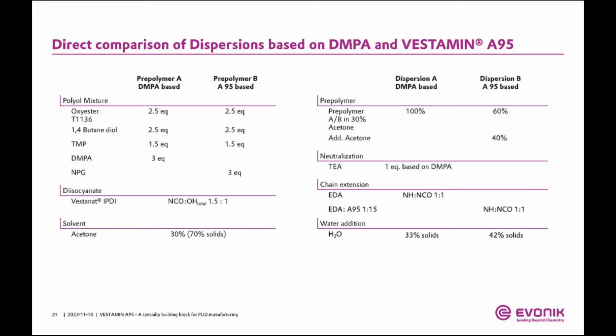In this case, with the A95, we do actually the chain extension and adding the emulsifier at the same point, right? When you use the DMPA-based method, you add the emulsifier right from the start in your prepolymer synthesis, so it doesn't matter to wait with the chain extension until you add the water. In the A95 case, you are adding the hydrophilicity at the point when you do the chain extension. So this needs to be done before adding the water, because you need to hydrophilize before you add the water. And this chain elongation then causes higher viscosity, and that's the reason why we add some more acetone to get the viscosity under control, and also it controls the heat a little bit better.